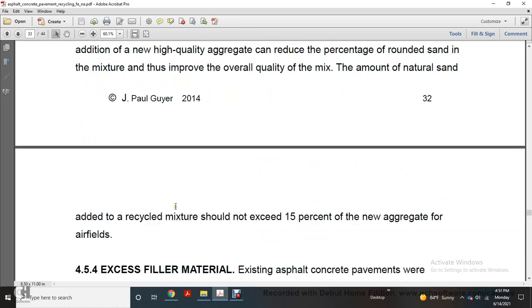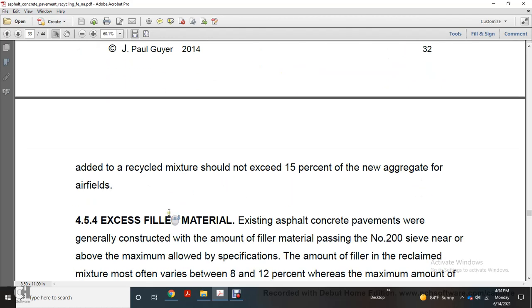The amount of natural sand added to the recycled mixture should not exceed 15% of the new aggregate for airfields.